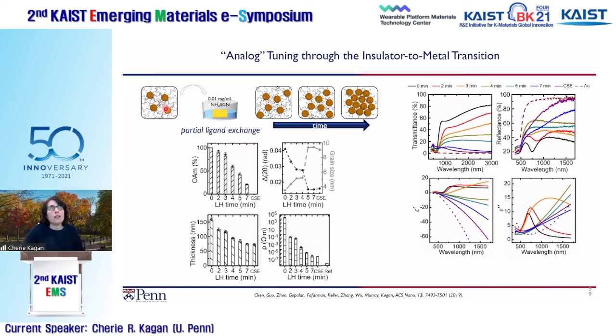If we take the oleylamine-capped particles and immerse them in thiocyanate, we can control it dilutely, and so control the degree of ligand exchange. As we do that, you can measure how much of the oleylamine ligand comes off. We can see how the particles come together and start to fuse. And we can see, for example, how the resistivity, we can sort of dial in that resistivity.